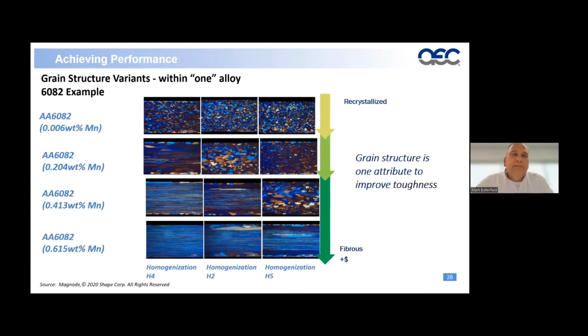One thing I've run into, speaking with customers in the past, is we can start off with an alloy, in this case 6082. When we looked at 6082, it was a fairly large band, with some overlap. If you were to look at that alloy, you would see some overlap from 6061, 6008, 6005. So first we're looking at the chemistry itself, but then we also need to understand what type of grain structure we are looking for. Here's an example of three different homogenization cycles with slight variations of manganese and the impact that it has relative to the structure of the product.